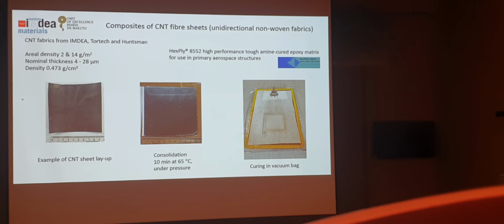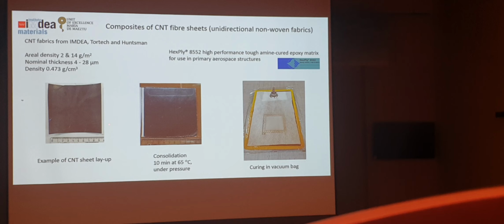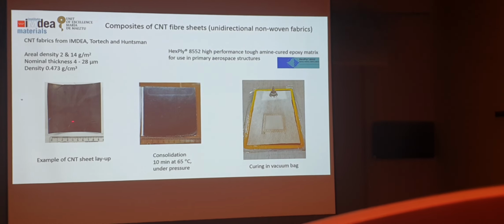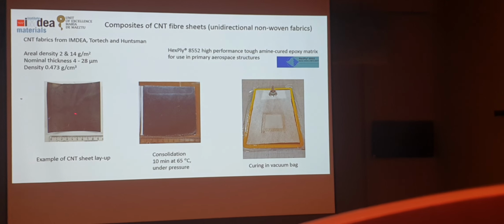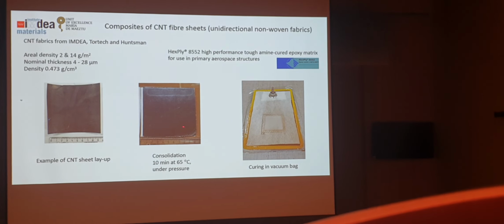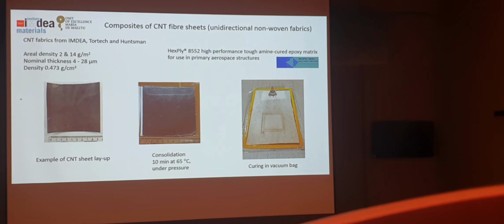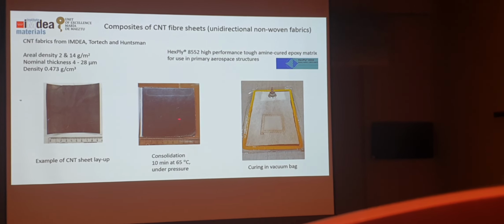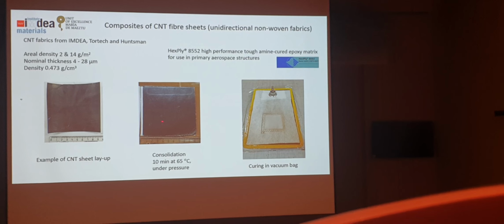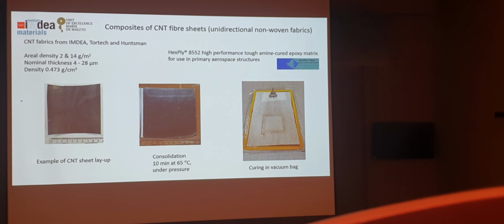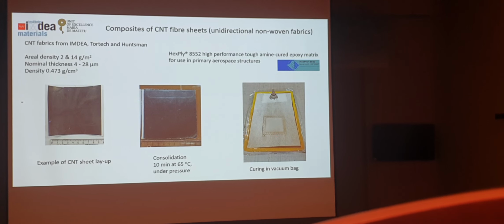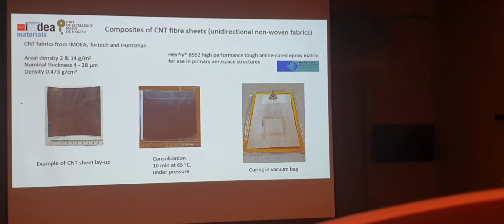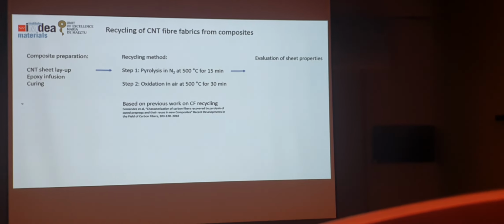So to do this recycling study, we produced the largest composites we could with the material available. These are sort of 10 by 10 sheets, and we infused them with commercial thermosets. For most of these studies, we used an epoxy from Hexcel, which is an aerospace grade epoxy. This is infiltrated, and we need to apply a bit of pressure for this to infiltrate, and then we cure it with a vacuum bag. This is about as industrial as we can go with the format of the materials we have at the moment. But these are recognized as reasonably reproducible composite processing methods. So there's not much porosity and so on.